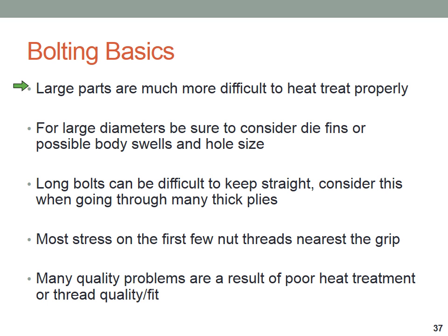They become much more difficult to heat treat, and heat treat is essentially what gives us all of the properties of a fastener. For large diameter fasteners, you also have to consider that they're typically hot formed, and those can come with die fins and some tooling marks. Long bolts can be difficult to keep straight through the heat treating process. If you're trying to get through 18 inches of steel with a 1/16 of an inch oversized hole, sometimes that can be tough with really long bolts.